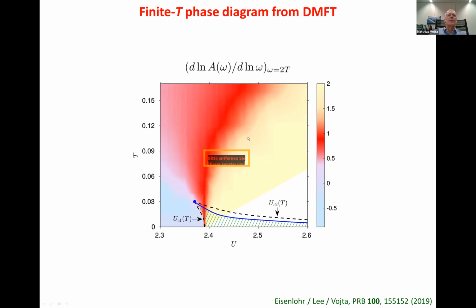This originates, and you can see this very nicely at this point down here, which is where the metastable insulator starts at T equals 0. So this has nothing to do with the physics of this critical endpoint, nor with this first order transition line, but emerges from that point down there. This has escaped attention so far, because in this regime of the phase diagram, the thermodynamically stable phase is the metal, so people did not pay much attention to the insulator.